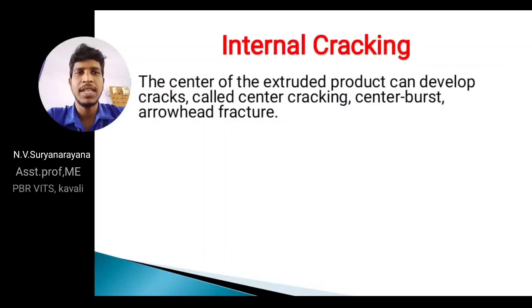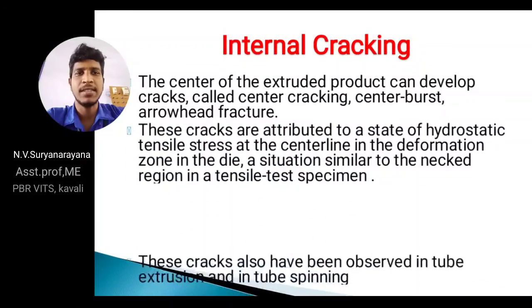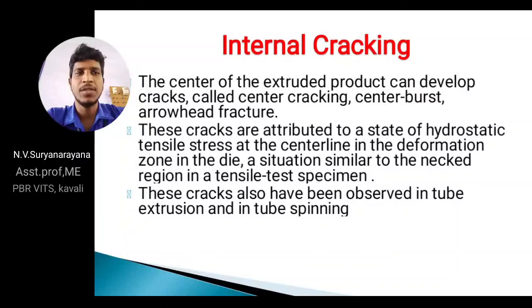Next, coming to internal cracks, the center of the extruded product can develop cracks called center cracking, center burst, or arrowhead fracture. These cracks are attributed to a state of hydrostatic tensile stresses at the center line in the deformation zone in the die, a situation similar to the necking region. These cracks also have been observed in tube extrusion and in tube spinning.